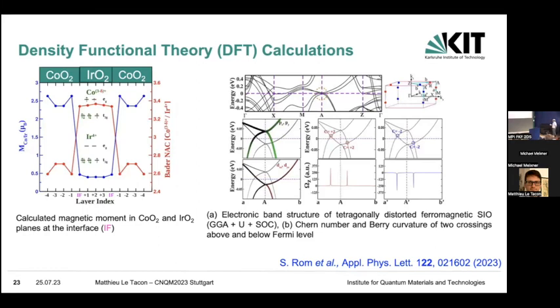The only thing is that, of course, when they calculate this, they found that when you distort the iridium layer, making the tetragonal distortion or stabilizing the pseudo-tetragonal phase, this layer was actually ferromagnetic, which is not something that we have, because you really need to have it in contact with the cobaltate layer.